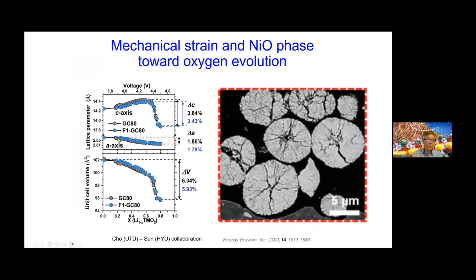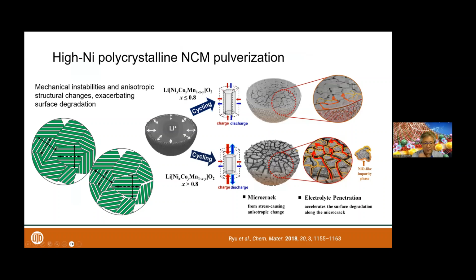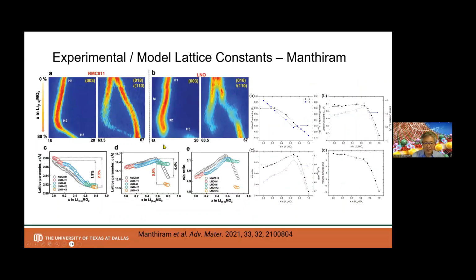So the next problem, how can we address this problem? Because this is the source of the problem: each cathode particle is going through the mechanical deformation, going through the fracture, liquid electrolyte penetrating, and on the surface a nickel monoxide-like phase is forming and losing the capacity. This is the conventional, typical process of capacity degradation. So how do we address this problem? In order to address that, the next thing we have done was how to control the volume change.